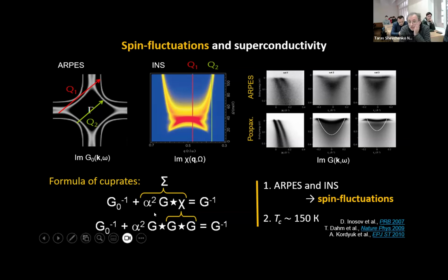Here I want to say, without going into details, that this formula just represents how the electronic spectrum of cuprates is built. Here G is the Green function, and it represents the density of states. So in simple words, the important quantity which you can get from these spectra is called the quasi-particle self-energy. It is just a certain convolution of the density of states with the spectrum of excitations. In the case of ordinary superconductors, it was the phonon spectrum, and now it was shown that it is a spectrum of spin fluctuations.